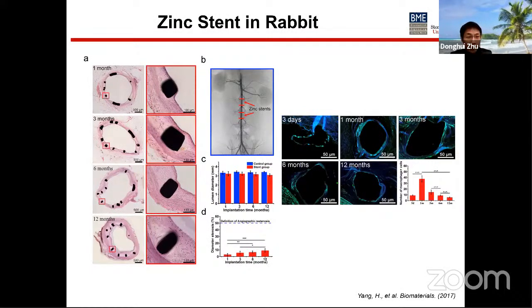From the macrophage staining, there was no acute inflammation 3 days after implantation. The inflammatory cells, largely macrophage, increased after 1 month, reaching the largest level at 30 days, probably largely due to the degradation product after a while. Then a decreased trend of inflammatory macrophage infiltration was observed after 3 months, gradually returning to baseline after 6 to 12 months.